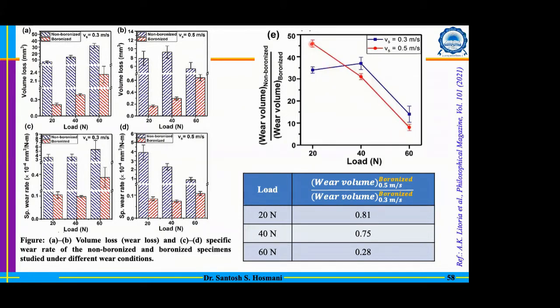What it says is that initially the difference between the boronized volume with respect to the non-boronized surface, you will actually lose the advantage associated with the hard surface as you keep on raising the load. But still, here you can see that at very low load, the boronized surface is behaving extremely well. The difference between the wear volume for the non-boronized versus the boronized is about 45 times. It is better. However, at higher load it is only about 10 times better improvement you will see with the boronized surface. But still, that 10 times is not really a bad value. So it's really good in that regard.